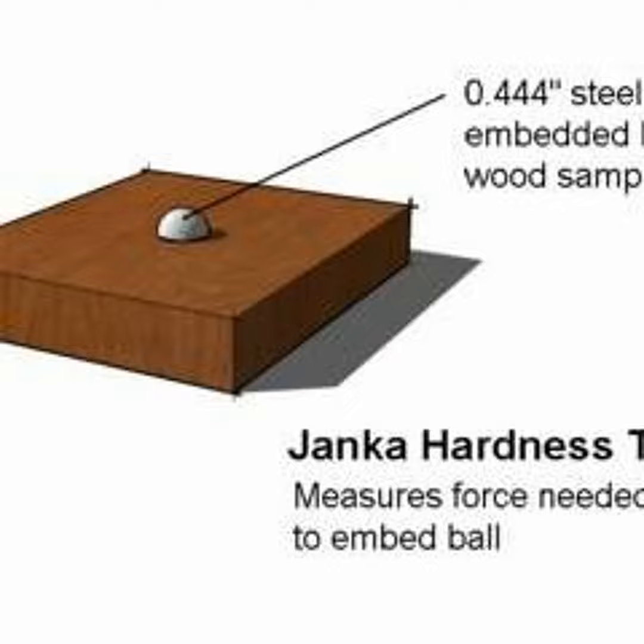But for the most part, black walnut is going to have a ring porous structure. Now, they have almost identical Janka hardnesses, but because the pores in cherry are quite a bit smaller and they're spread all over the place, cherry feels a lot harder to chop a mortise in than walnut. Substantially harder, even though that hardness is almost the same, within 10 pounds per square inch of one another.